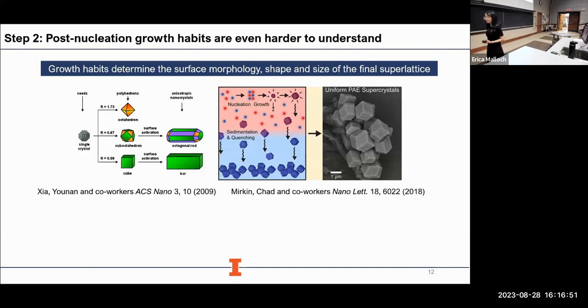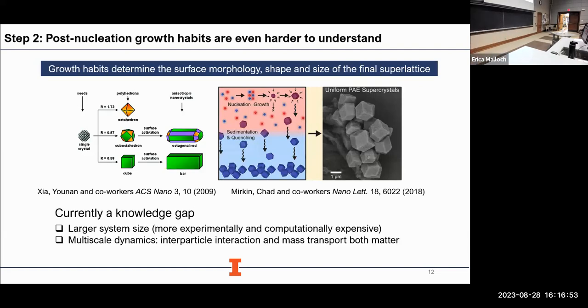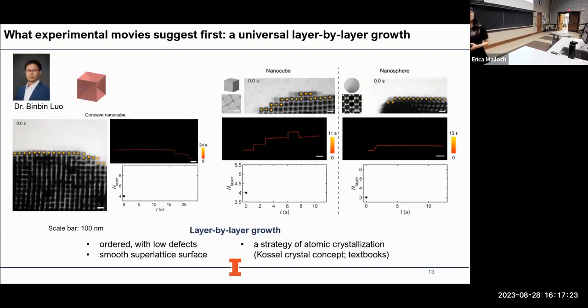It turns out post-nucleation growth habits is an even harder question to study than nucleation, because you are dealing with a much larger system post-nucleation. As a result, it's both experimentally and computationally more expensive. In addition, for growth habits, not only does the interparticle interaction matter, but mass transfer properties such as diffusion and flux also start to matter. That's why it becomes a complicated multi-scale dynamics question. So we took on the experimental challenge anyway.